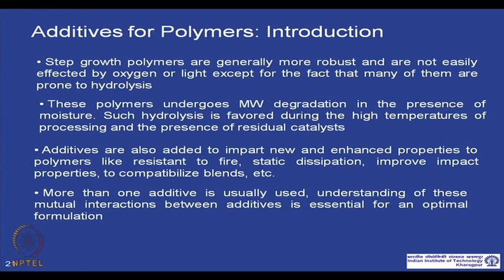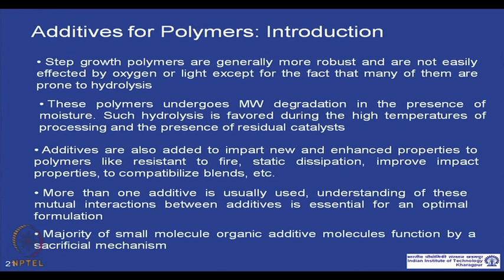And generally these small organic additives work by a sacrificial mechanism. By the term sacrificial mechanism, I mean that they destroy themselves and protect the main polymer which you want to maintain or retain. So, basically they destroy themselves by doing some chemical reaction and sacrifice themselves to protect the main polymer in concern.